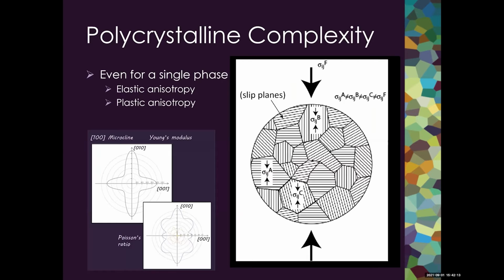And so as a reminder, polycrystalline systems under deformation are fairly complex. This illustration to the right shows a polycrystalline aggregate where even for a monometallic phase aggregate, you have grains that are all oriented differently. And then these sets of lines inside the grains remind us that the crystal lattice is oriented in different directions and that we're going to have slip planes in each grain that are oriented differently. So if we look for the boundaries of the polycrystal, as we often do, and we apply a stress, we want to know how does the polycrystal decide on its aggregate behavior.